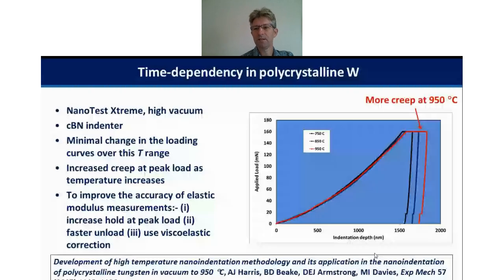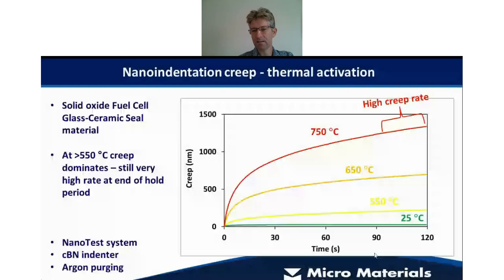But what we do see is greatly enhanced creep in the hold period at peak load. And we need to take that into account if we want to get accurate elastic modulus measurements from the unloading curve. The various strategies to do that involve increasing the hold time at peak load, unloading more quickly, or using a viscoelastic or another analytical analysis.